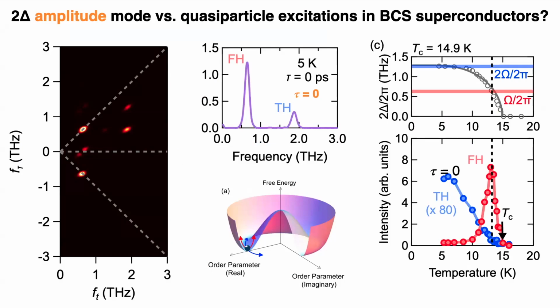We've been doing work with looking at collective modes in superconductors. And so there's been a lot of work, as you may know, about people looking at the amplitude mode in conventional superconductors, the so-called Higgs mode in superconductors. I prefer the old school language amplitude mode, but 2D terahertz provides a particularly diagnostic way of looking at some of these particular spectral signatures, and in particular distinguishing the amplitude mode from its almost degenerate continuum of quasi-particle excitations, which go at 2 delta.